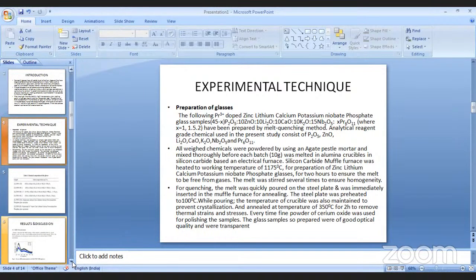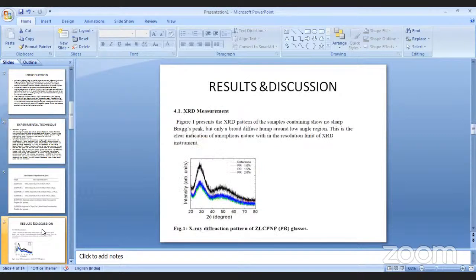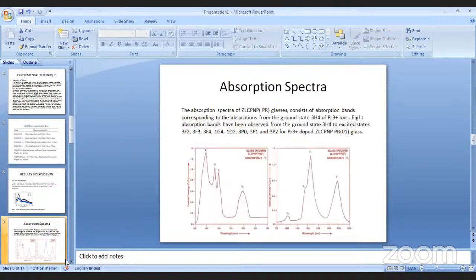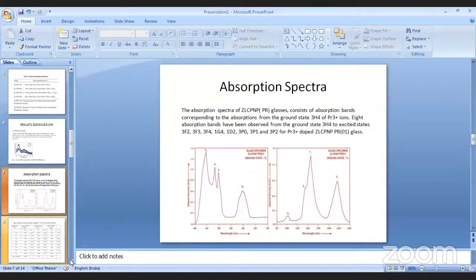Here I'm showing my results for the sample glass. Here is the XRD pattern of the prepared sample glass, which shows no sharp Bragg peak but only a broad diffuse bump around the low angle region, confirming the amorphous nature of the glass sample. And the absorption spectra is shown here. There are 8 absorption bands observed from the ground state level to the excited states.